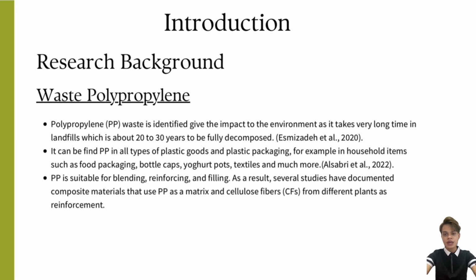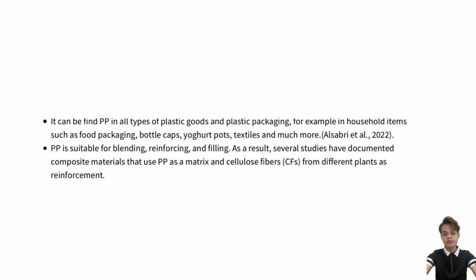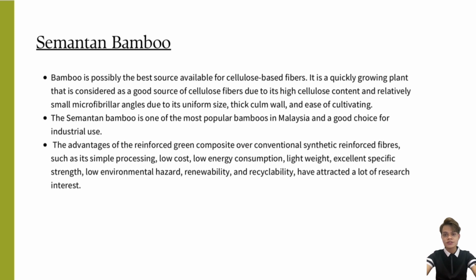As a result, several studies have documented composite materials that use PP as a material and cellulose fiber (CF) from different plants as a reinforcement. Bamboo is possibly the best available source of cellulose-based fibers. It is a quickly growing plant that is considered a good source of cellulose fiber due to its high cellulose content and relatively small microfibrillar angles. One of the most popular species of bamboo in Malaysia is Semantan bamboo, selected as a good choice for industrial usage because of its uniform size, thick culm wall, and ease of cultivation.